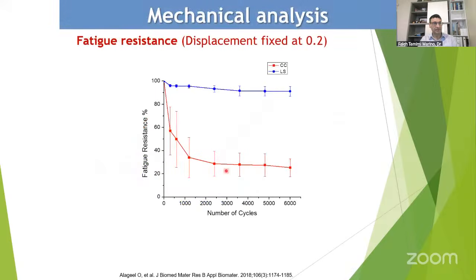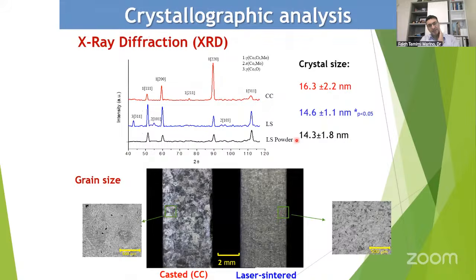This is the fatigue resistance over 6,000 cycles, and you can see that with cast metal it goes down over time, but with laser sinter metal it's very stable. The reason for this is that besides the organization of the material, which is very good for laser sinter metal, it has also another benefit. And it has to do with a property of metals, which is the grain size.